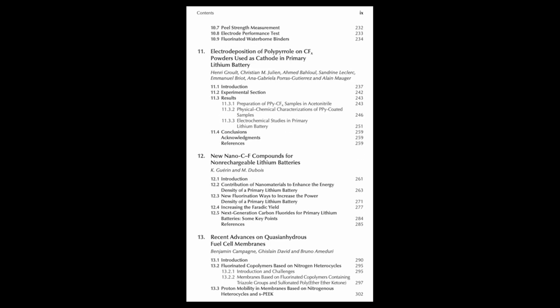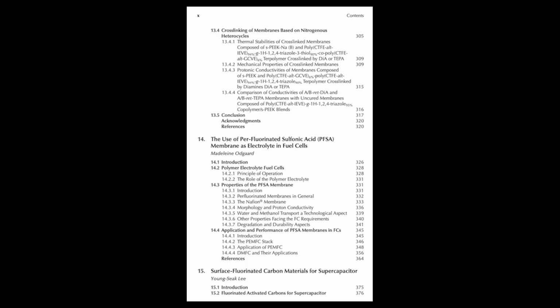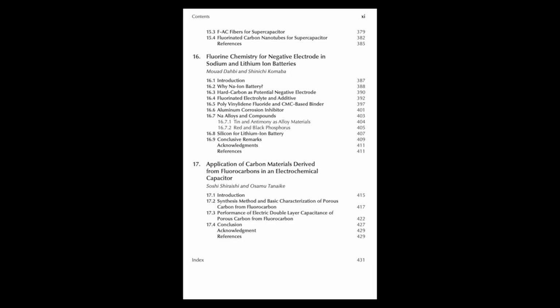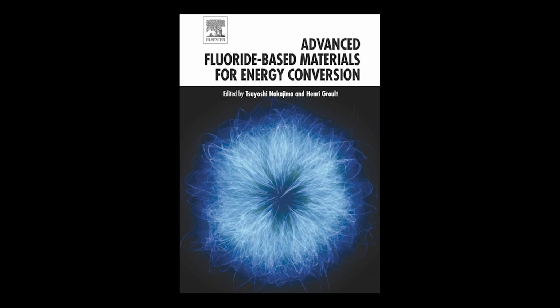Interestingly, X-ray diffraction (XRD) data suggests that this process can slightly alter the crystal structure just in that surface region. It makes the peaks in the XRD data a bit less defined, a bit broader. Table 2.3 and figure 2.10 showed that. And another technique, XPS, X-ray photoelectron spectroscopy, confirms the presence of fluorine on the surface in different chemical states.